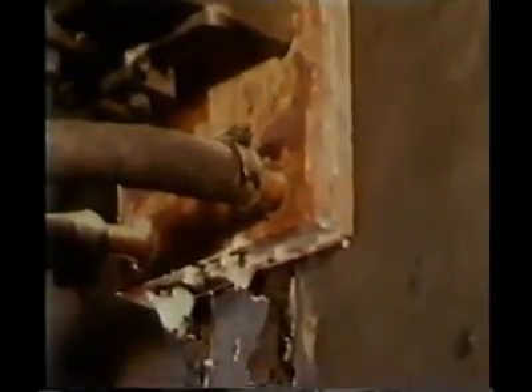Thus, the rate of weld deposition and the extent of plate edge fusion is under very accurate control at all times. The weld produced is free from such internal defects as porosity and slag inclusions, which are sometimes associated with other systems of automatic welding.